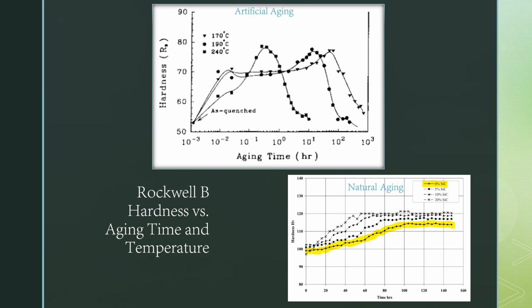Wow, you can clearly see the peak aging time for 170 degrees Celsius is 48 hours, 190 degrees Celsius is 12 hours, and 240 degrees Celsius is 15 minutes. For the artificial aging, the hardness increases to the maximum hardness and decreases afterward. Natural aging shows a hardness increase and a plateau after 100 hours. So, the trend we're seeing is that artificial aging shows a maximum hardness at peak aging, and the greater the temperature, the lower the required holding time. With natural aging, it takes much more holding time, and the hardness value reaches a maximum.